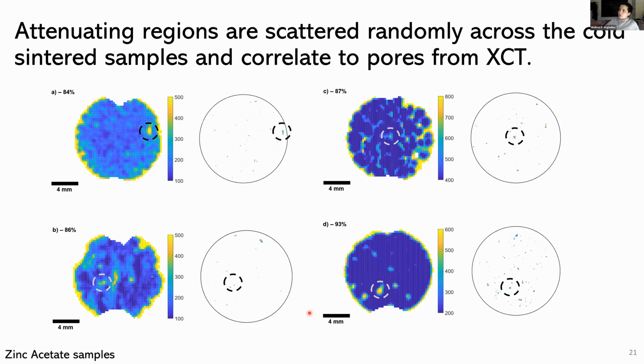So we think that it's a combination of a few different things. The CT data you're seeing here is the sum of the pores through the depth of the sample, so that you can have a one-to-one comparison to the ultrasound. And essentially, it's doing a relatively good job of mapping some of those features, but some of these features were actually rather fine in terms of features that were essentially just capturing flaws along those grain boundaries that, although we're not necessarily imaging them, they're essentially affecting our ultrasonic response in a way that wouldn't show up in the CT.